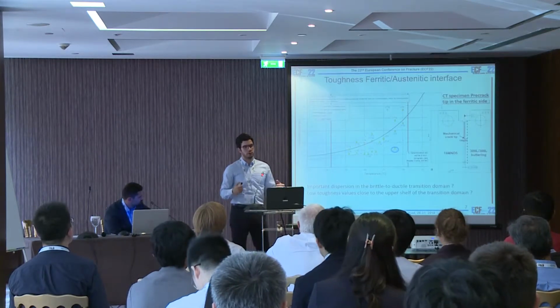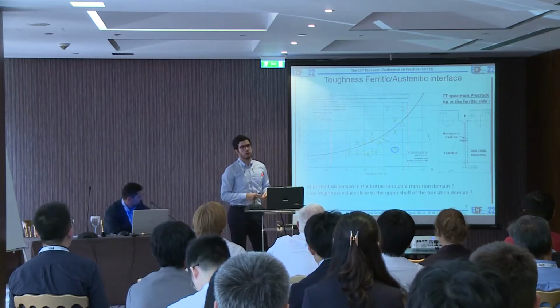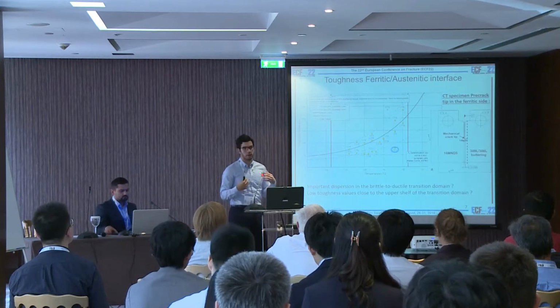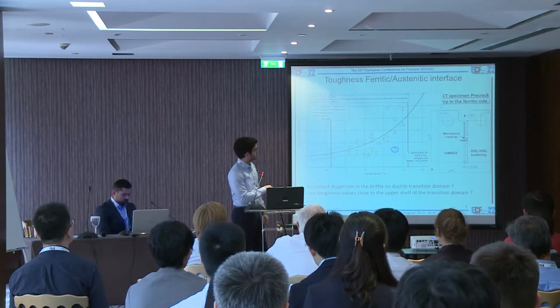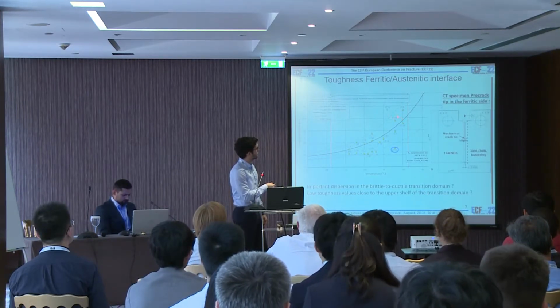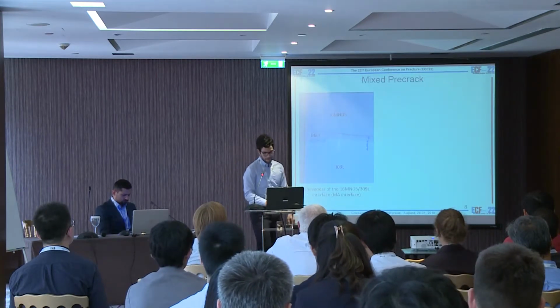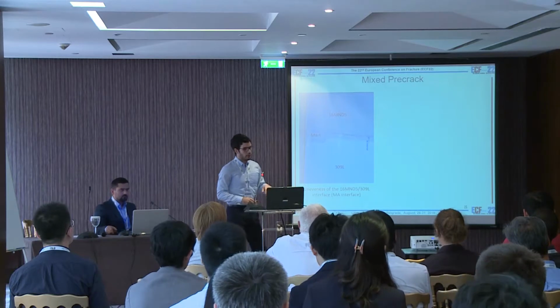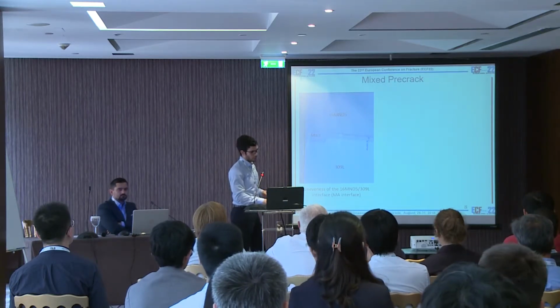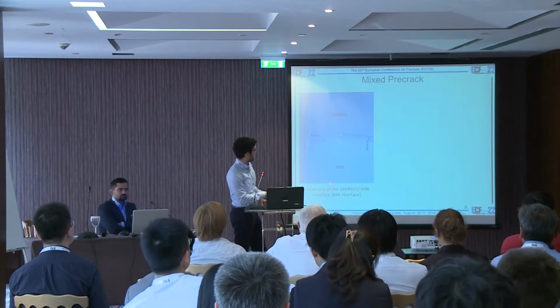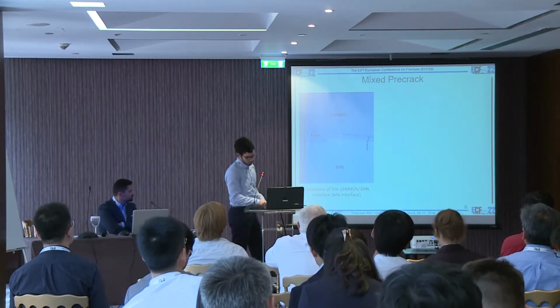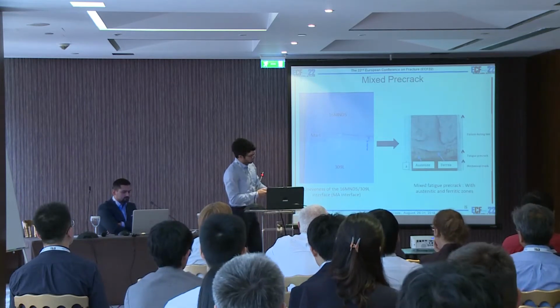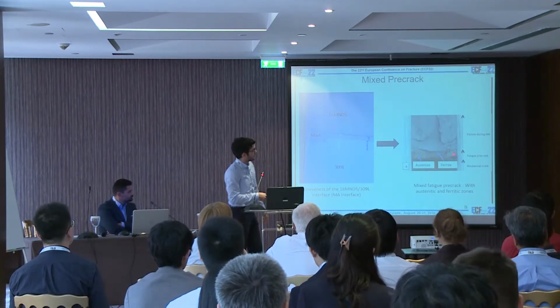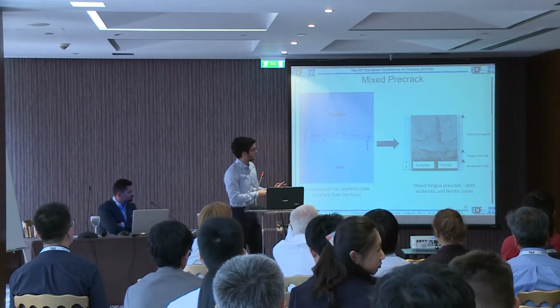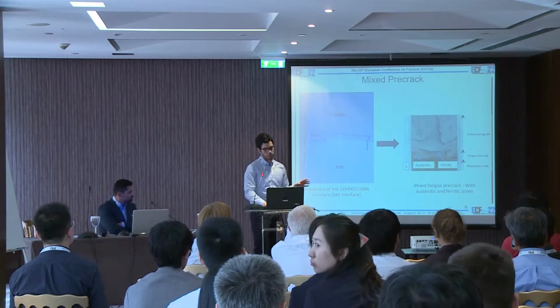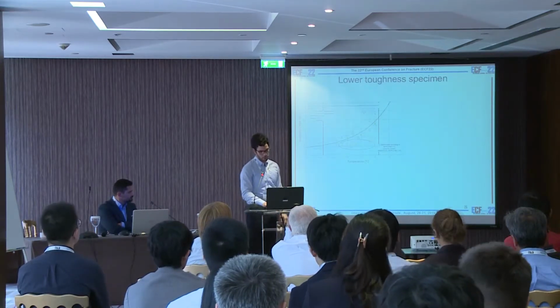So we have to do some analysis of the fracture surfaces in order to understand the underlying fracture mechanism responsible for these differences between, for example, this value and this value at the same temperature. So, first analysis of the fracture surfaces shows that because of the unevenness of the MA interface, which we see right here, for some specimens we obtain mixed fatigue pre-cracks. So fatigue pre-cracks with both austenite and ferrite. And that most certainly will affect the crack initiation and propagation.